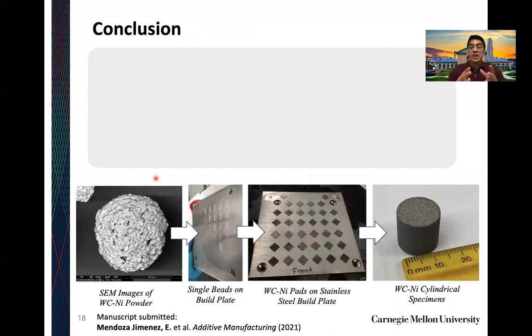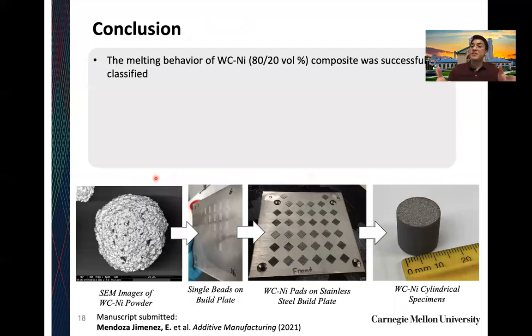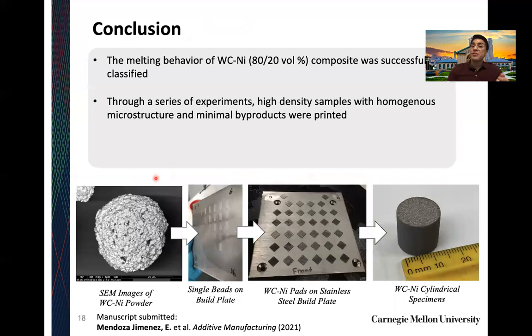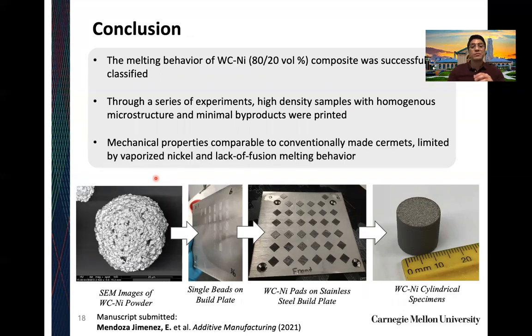So, in conclusion, we show that the melting behavior of tungsten carbide nickel, an 80-20 composite, was successfully classified. Through a thorough series of experiments, we managed to print high density samples with a homogeneous microstructure and minimal byproducts. And finally, the mechanical properties, i.e. the hardness, were comparable to conventionally made cermets, and we realized that the mechanical integrity of the cermet is limited by the vaporized nickel at very high energy densities, as well as the lack of fusion porosity at much lower energy densities. And I always like to end my talks with a graphical representation of what we did.